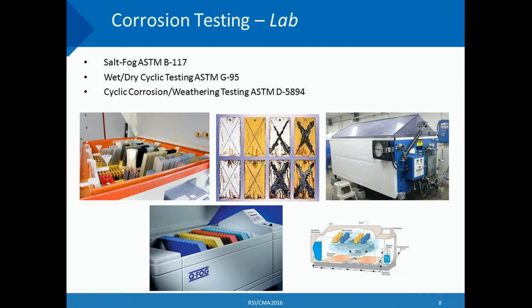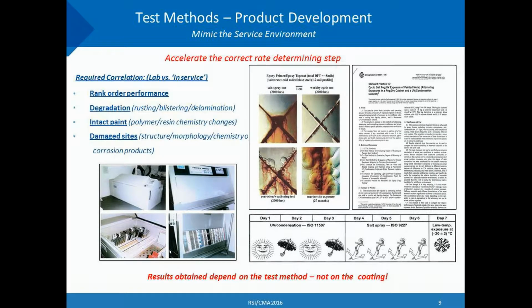the ASTM D5894 test, which combines cyclic corrosion testing with UV conditions too. So you take both together and you now have the right circumstances for mimicking what happens in real life by including cyclic corrosion with UV weathering characteristics all in the same test. This slide shows you how this methodology mimics the service environment by using the test chambers, as I mentioned.